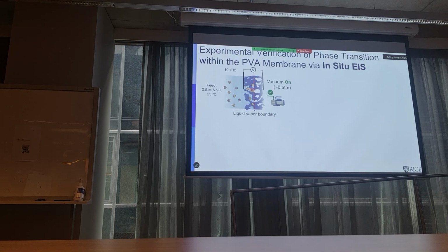So this will be wet with the ions, but now when you have become vapor dry, you will not have any ions here. So you should get high resistance because there is discontinuity of this conducting. Now here you have vapor water, but the ion cannot be there. Not conducting, you should get very high resistance. And if you turn off the vacuum, immediately all the pores will be filled by electrolyte, you should get low resistance. And indeed, this exactly, we are now working on it and modifying it and hopefully write a paper.